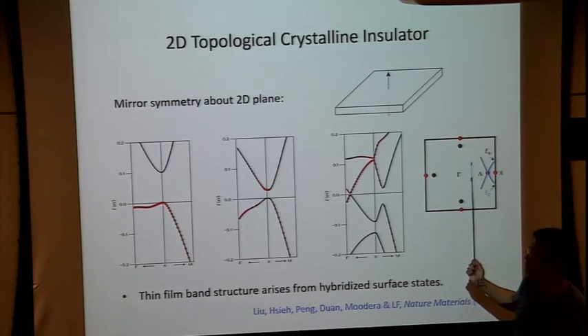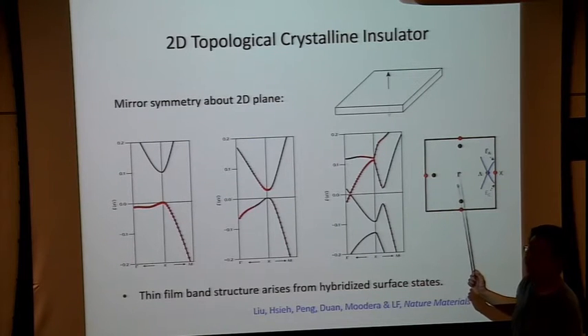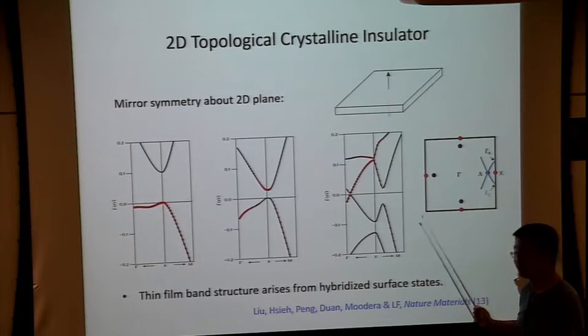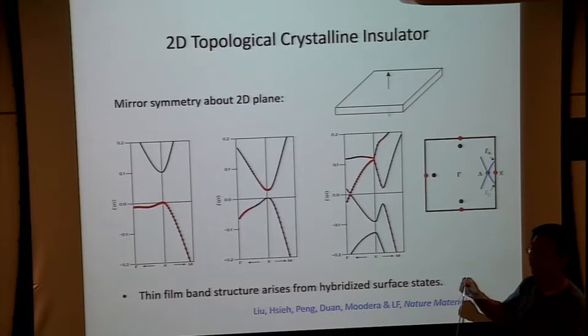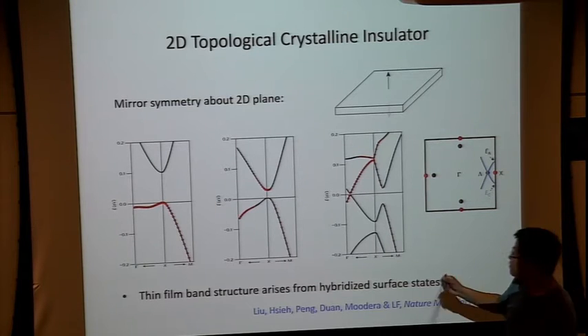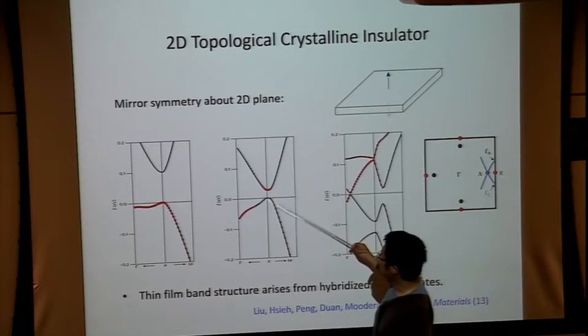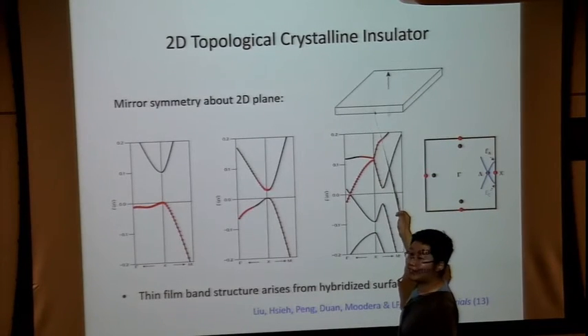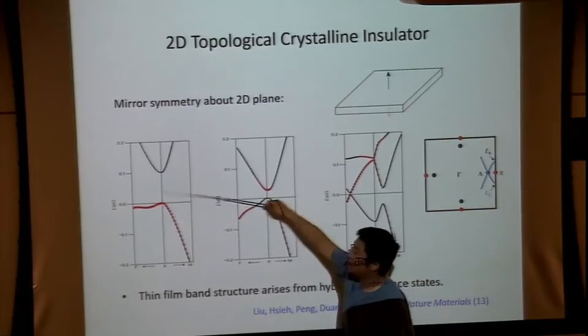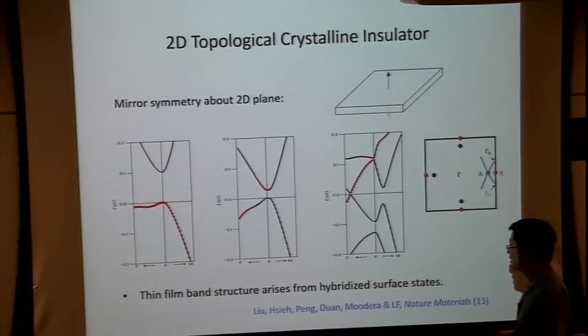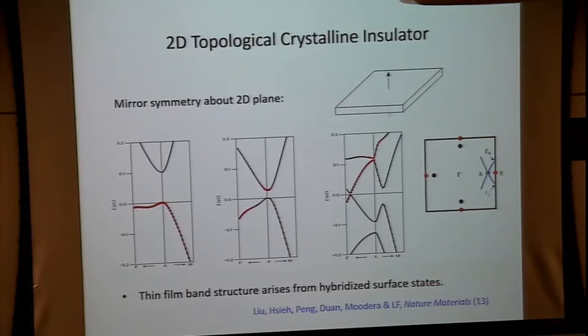In other words, if I compare band structure of thin films of tin telluride and lead telluride, they are very different, because in lead telluride, in the 3D limit, there are no surface states, but in tin telluride, there are. So even when you take a thin film, when the top and the bottom surface states strongly hybridize to open up a gap, the low energy band structure is basically coming from the hybridized surface states. They are very different from the bulk states.